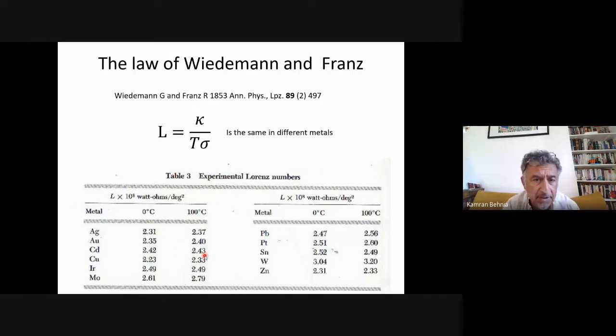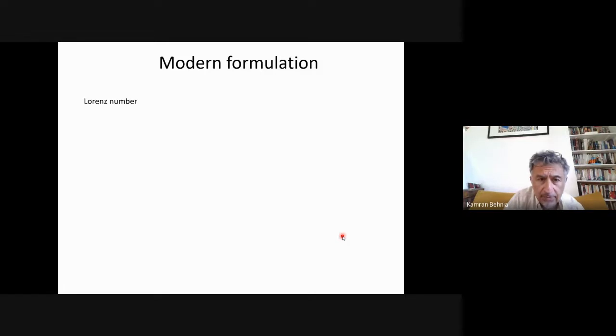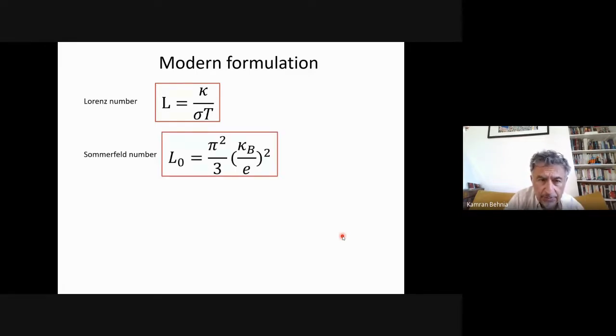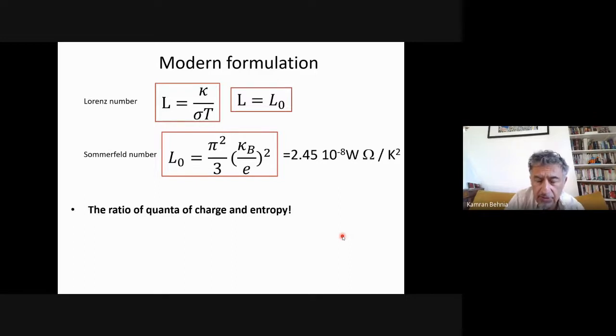In the sense that if you measure the electrical resistivity of a metal at room temperature, and you measure its thermal conductivity at room temperature, and you look at the ratio of electrical and thermal conductivities divided by temperature, you find something which is almost the same in different materials. And the modern formulation is that this Lorenz number, the ratio of these two conductivities divided by temperature, should match the Sommerfeld ratio, which is the ratio of Boltzmann constant and the charge of electron, times pi squared over 3. This is something that is now well enshrined in the quantum theory of solids.